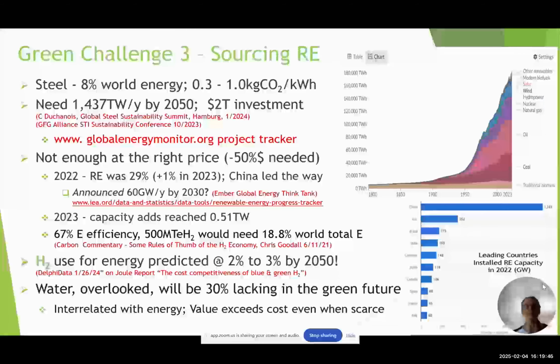Third challenge is resourcing renewable energy. We, as a steel industry, use 8% of the world energy, and 0.3 to 1 kilograms of CO2 is produced per kilowatt hour, depending on the source. We need 1,437 terawatts by 2050, and that's a $2 trillion investment. There's not enough at the right price. We need a 50% cost reduction. In 2022, 29% was renewable energy. The chart at the right-hand side here shows predominantly all of the energy was basically from fossil fuels.